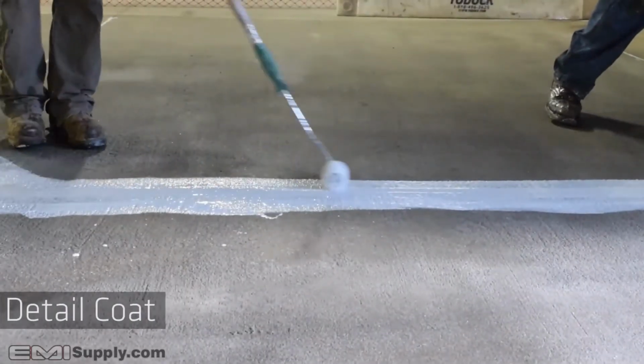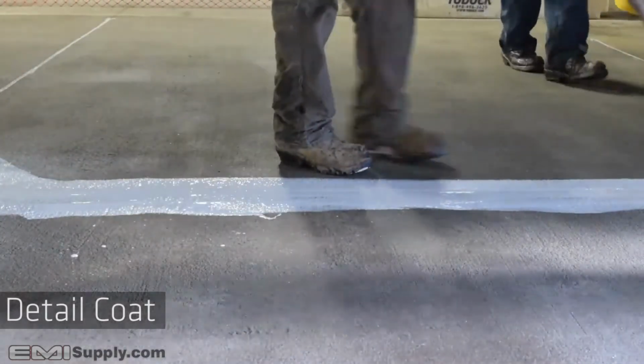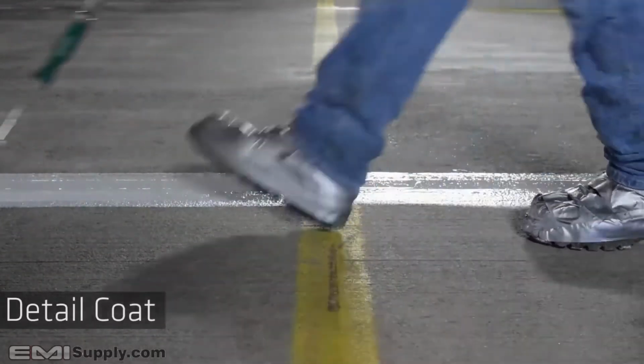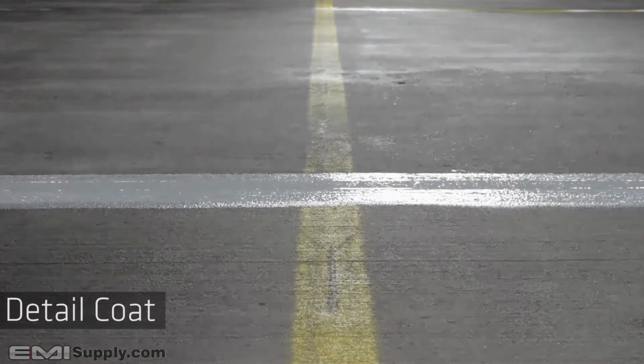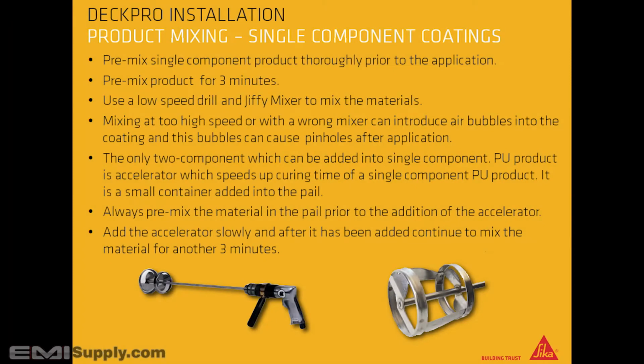Apply base coat with a roller 6 inches wide, centered over the joint or crack in a minimum thickness of 23 dry mils. Mixing for single-component coatings. Pre-mix single-component product thoroughly prior to the application. Pre-mix product for 3 minutes. Use a low-speed drill and jiffy mixer to mix the materials. Mixing at too high speed or with the wrong mixer can introduce air bubbles into the coating, and these bubbles can cause pinholes after application.